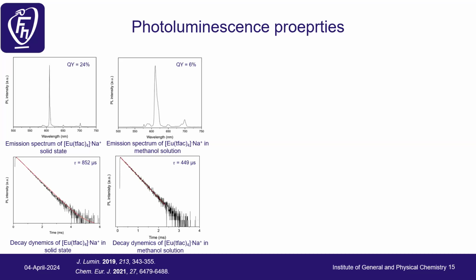state, and the lifetime is around 850 microseconds. And when we introduce methanol, we reduce the quantum yield, but also the lifetime, because we introduce more quenchers. In this case, methanol, we have C-H and O-H quenchers, which can influence, while here we are in solid.